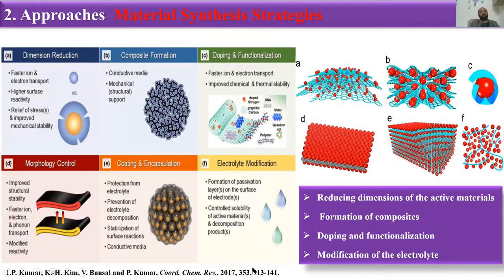So there are different approaches to improve the material synthesis of the supercapacitors. We can reduce the dimension size and form composites. With functionalization, we can improve the supercapacitor performance by controlling the morphology of the material during synthesis. Encapsulation can also benefit the improvement of capacitance, and we can modify the electrolyte, using different types of electrolyte and controlling their stability. We can utilize them in the synthesis for the desired results of our supercapacitor materials.